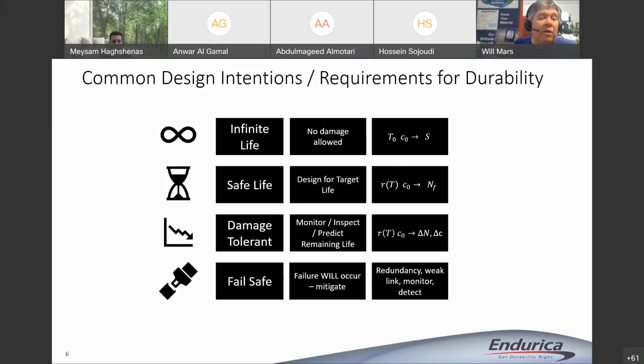And if your driving force on the crack is below the fatigue limit, then you have infinite life. And you can calculate this safety factor S, right? It says, hey, I've got a margin of 2 times relative to infinite life, or I've got a margin of 10 times, and then you're done. And like I say, it's a cheap approach, because you only need to test one or 2 things. Your finite element model only needs to look at the worst case loadings, and what you end up with is just this simple measure S.